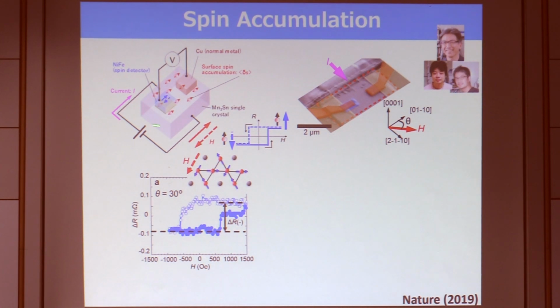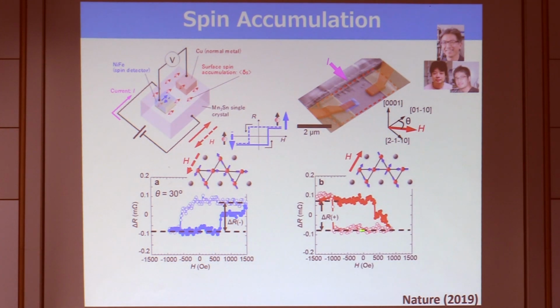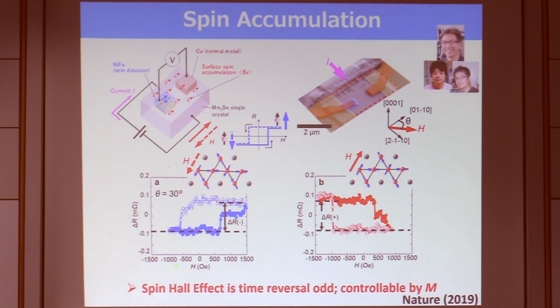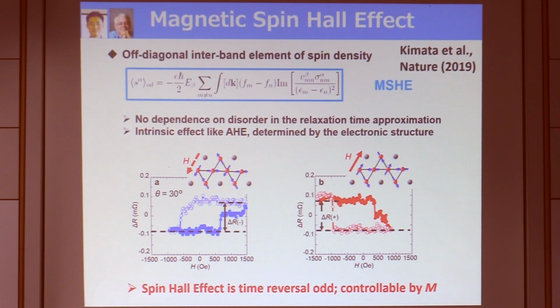Another interesting point is that because manganese tin is magnetic, you can rotate the spin texture by using a magnetic field. So we rotated this magnetic texture of manganese tin by 180 degrees, and did the same measurement and found this signal. Namely, the sign becomes opposite when we flip the magnetization. So this indicates that the spin Hall effect must be time reversal odd in this case, so the accumulated spin must change its sign. How do we understand this? This is an analysis made by Hua Chen and Allan MacDonald.